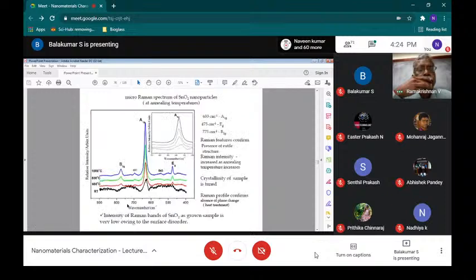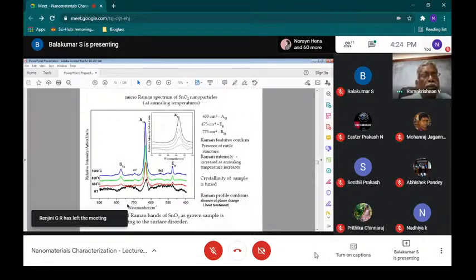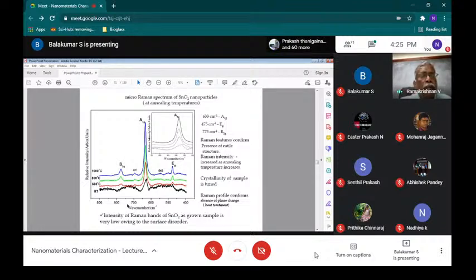Slide, please. So you look at room temperature, then 600, 800, 1000 degrees. You can see that the A1g mode becomes more intense, the 633 Raman line. After annealing, you don't see a new band, almost the same bands, and there is no shift in the lines. So the structure is not distorted; you only tune the crystallinity. If a new peak comes, or shifts or asymmetry, then it would tell you that a phase change has occurred.